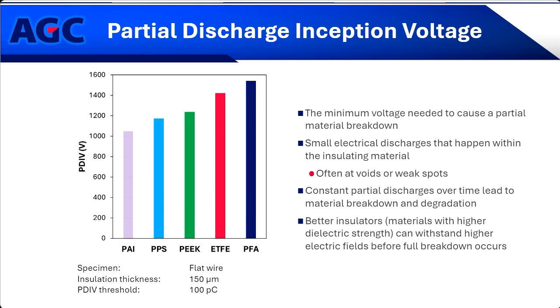Again, as I mentioned, having any kind of pinhole defect or delamination or cracking present is going to really affect your PDIV. Those specific partial discharges are not full breakdowns of the materials. So this is not the same as a breakdown voltage or dielectric breakdown test. Partial discharge, as it says, is just a small electrical discharge, a partial discharge happening within the material.